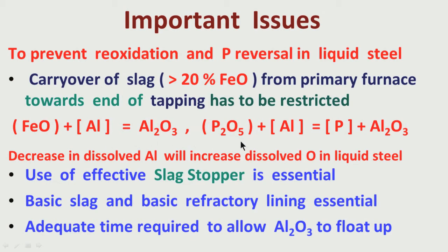Then phosphorus oxide: by controlling phosphorus, a lot of phosphorus has been transferred from the liquid steel to the slag. Now if this slag from the primary steelmaking comes to the ladle at the end of the tapping, then whatever phosphorus oxide is there in the slag might again react with aluminum, and there will be phosphorus reversal. So the possibility of reoxidation and phosphorus reversal in liquid steel will be there if we cannot control the carryover of slag from the primary furnace. So this is an essential requirement.